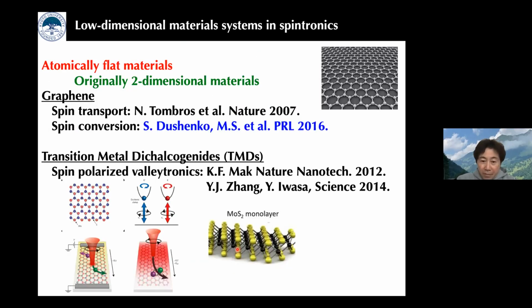Okay, so from here on, I introduce some milestone works using low-dimensional material systems. So the first example is, of course, atomically flat materials, because they are originally two-dimensional materials. The first important material is graphene, of course. And in 2007, a group at Groningen in Holland reported the first spin transport in single-layer graphene at room temperature. And this opened the frontier of graphene spintronics. So my group was also interested in this material. And in 2016, we reported the very efficient spin conversion, unipolar spin conversion in single-layer graphene. And I briefly introduce this topic later.